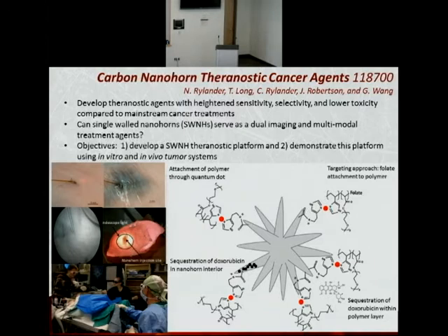We've done some dynamic light scattering to confirm our particle size. And typically right now our aggregate particle size is about 100 nanometers, and it confirms, I'll show that that's still very minimal in cellular uptake. What I show here is not only is us evaluating the particle important, we want to really understand the thermal dosimetry when we actually introduce these particles and heat with our laser.